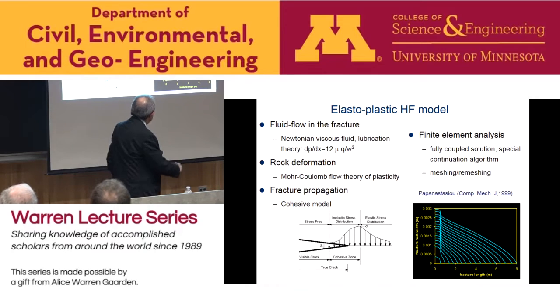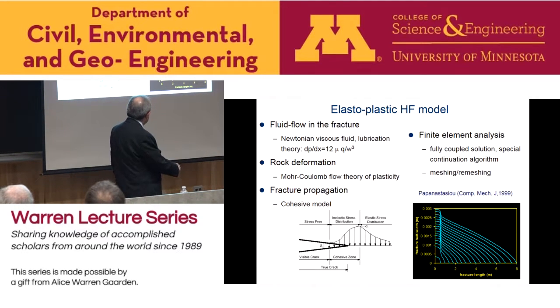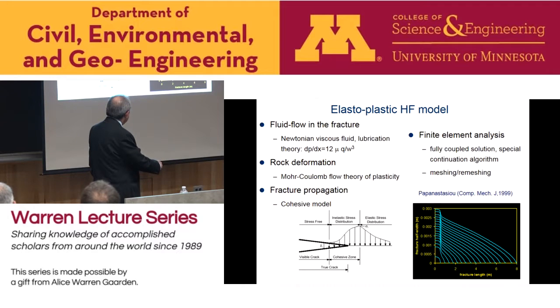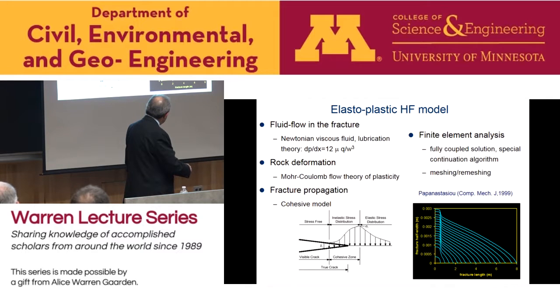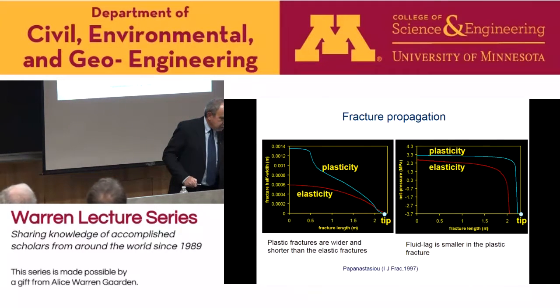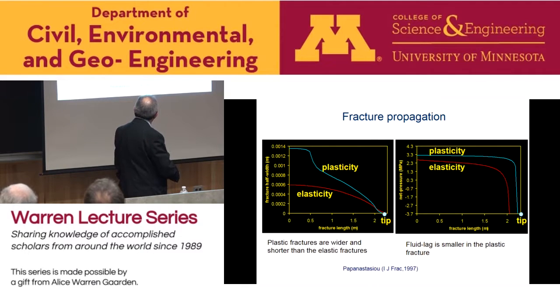I also saw some work on finite element analysis. In this picture, you can see the profiles of a propagating elastoplastic fracture. You just see a quarter of the profile as the fracture propagates. There is a quarter below, and the symmetric image on the other side, just ignoring the wellbore geometry. So the fracture starts from here and propagates. Now some of the results: we found that the plastic fractures are wider, and of course if they are wider, for the same pumping time they will be shorter. So shorter and wider than what elasticity predicts.